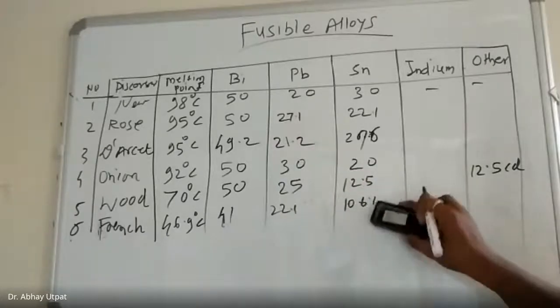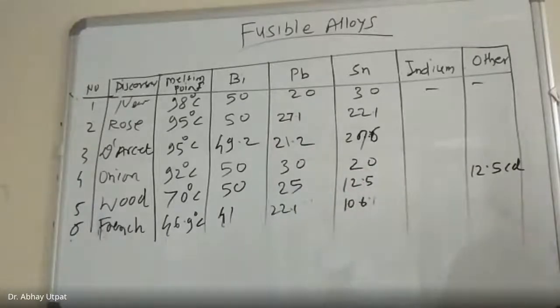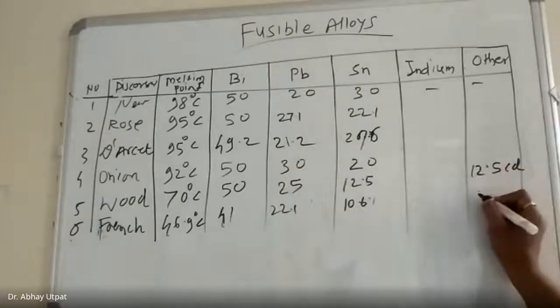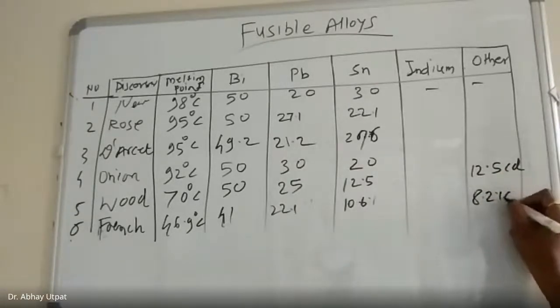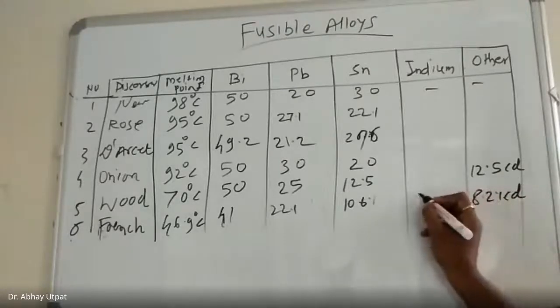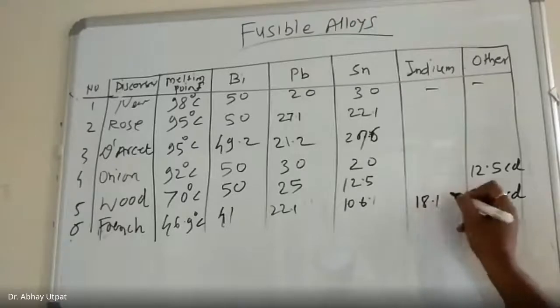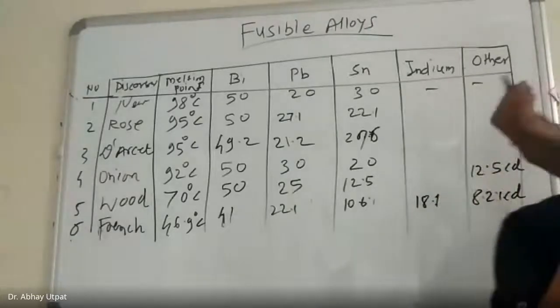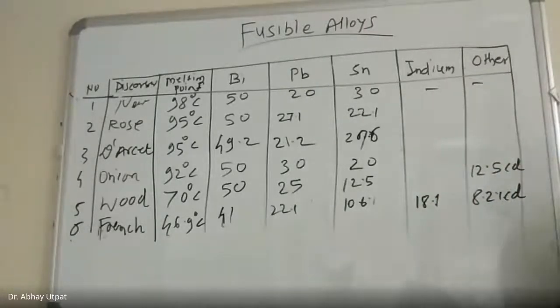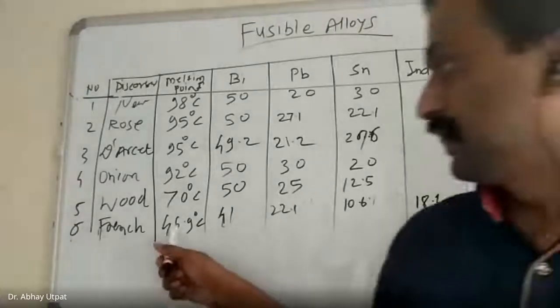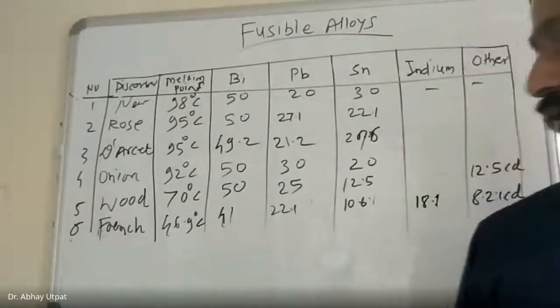22.1% lead, 10.6% tin, 8.2% cadmium, and here indium is used by him. 18.1% indium. 46.9 degrees Celsius.